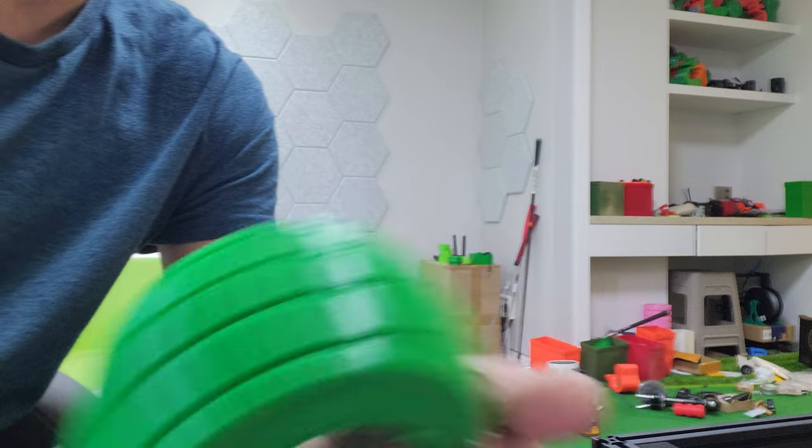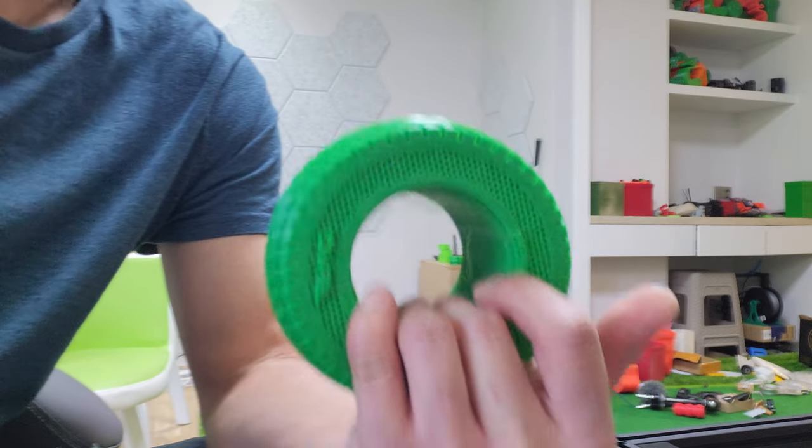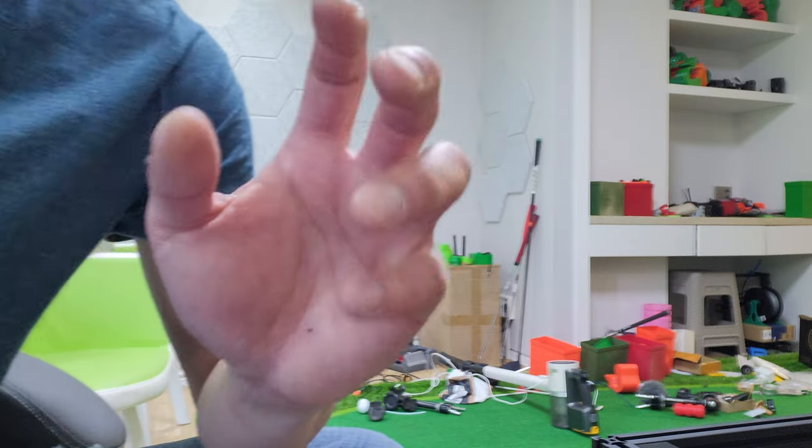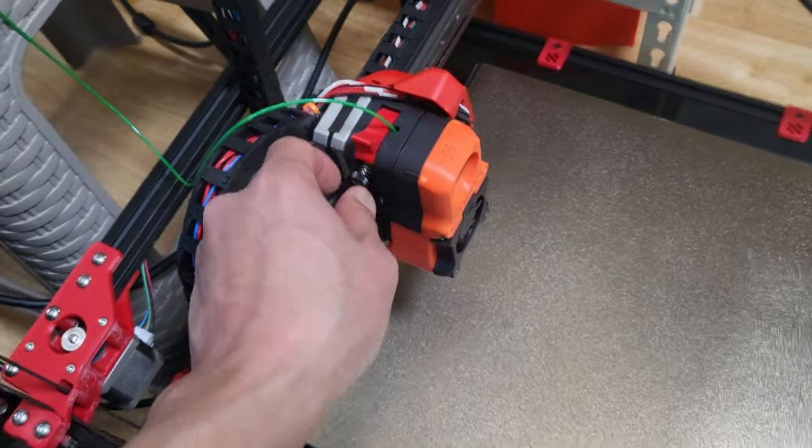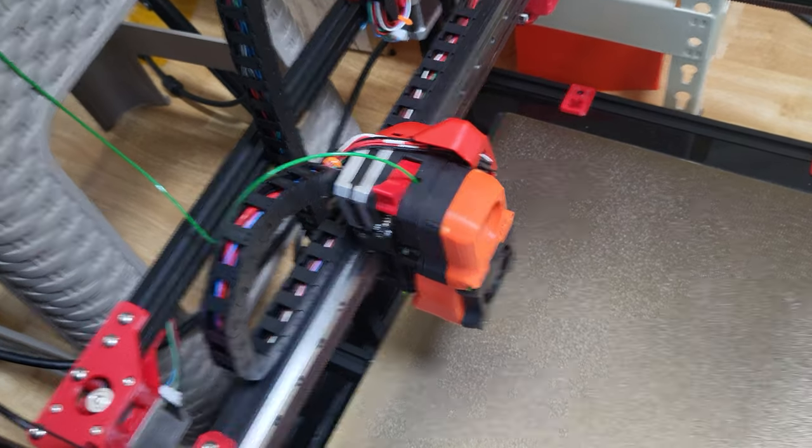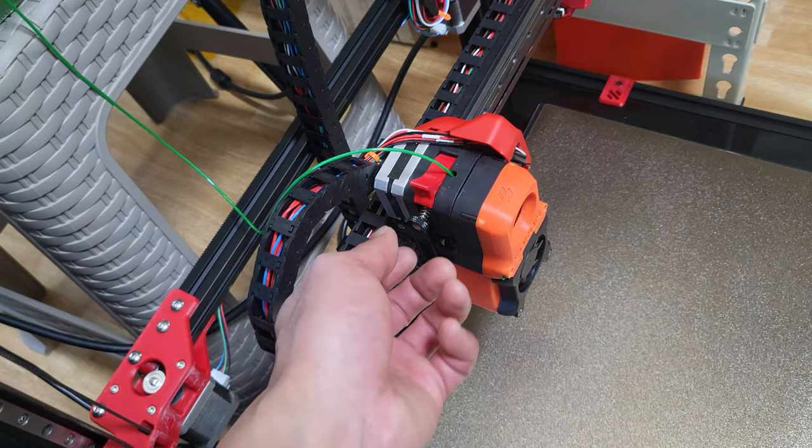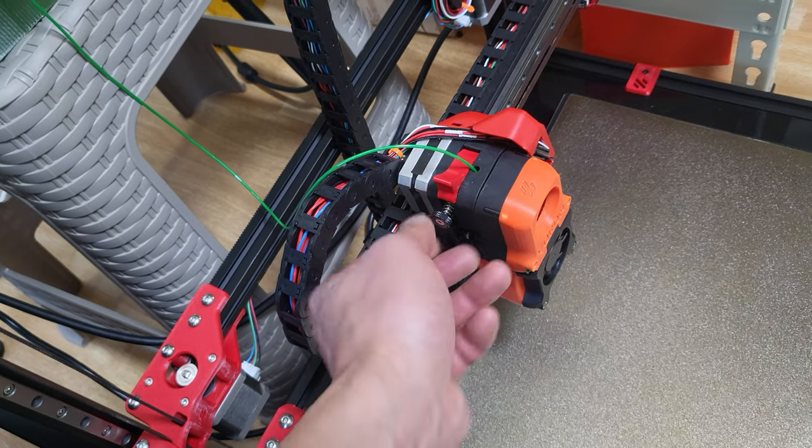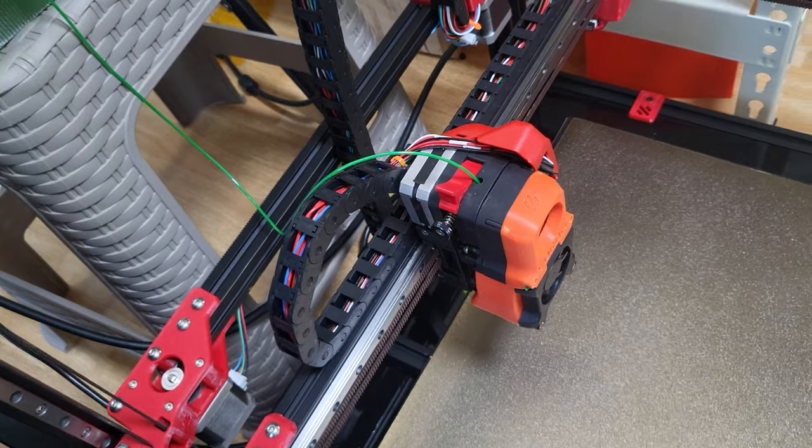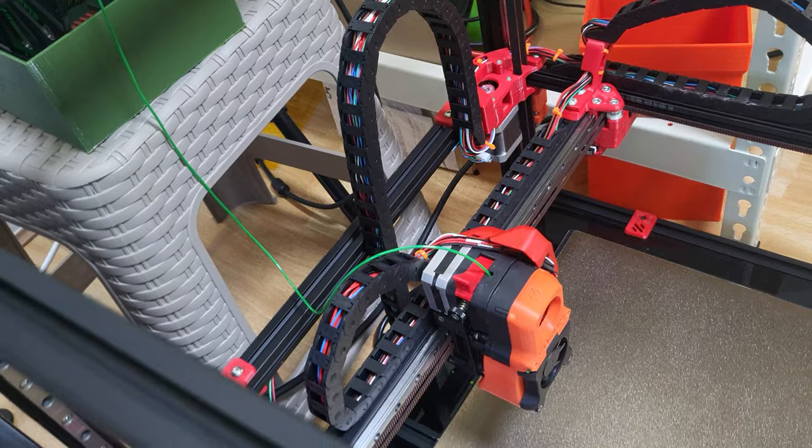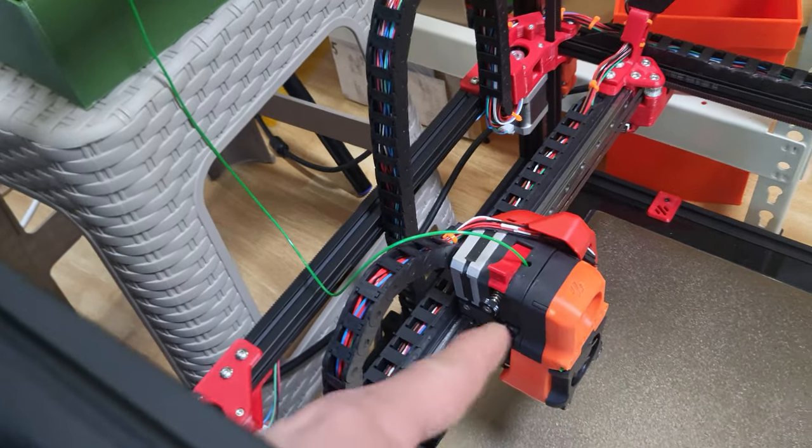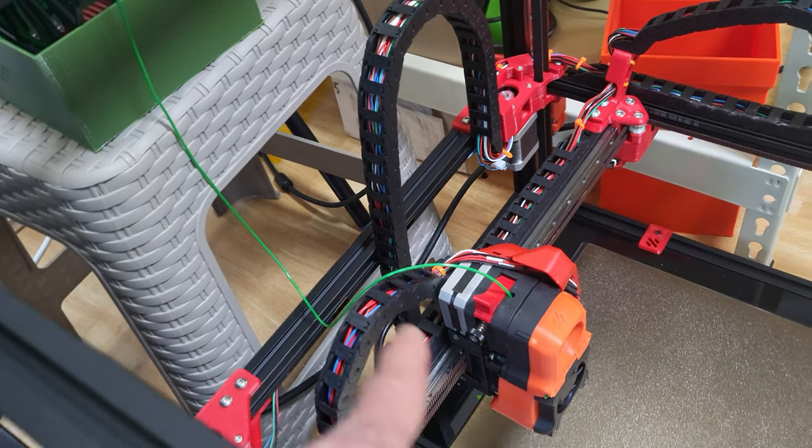So you do not need to upgrade to a stealth burner. Afterburner works fine for TPU. The only thing that I had to really do because it kept clogging is loosen the filament tensioner all the way until it pops off and then literally just do half a dial in after it attaches. So my dial is super loose and after that, zero clogging issues. I can push the filament with the dragon high flow here up to 45 millimeter cube.